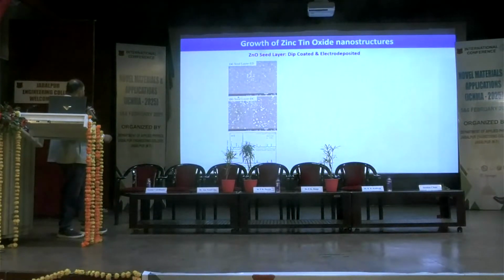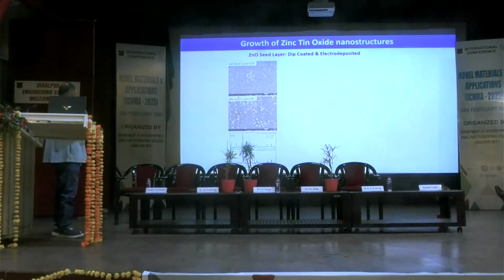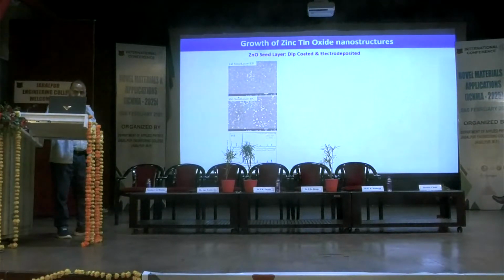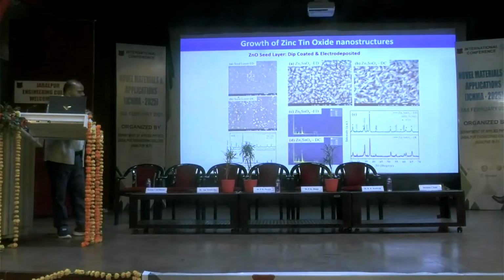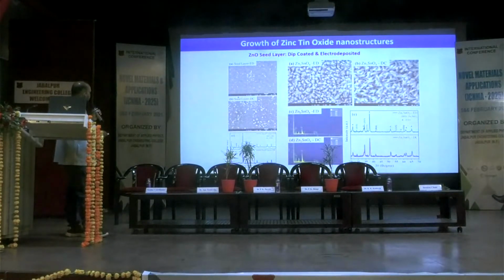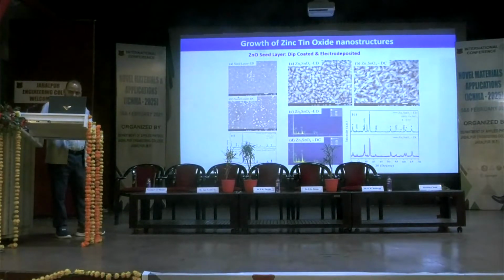So here you can see how the seed looks. Seed layer direct electrodeposition is more uniform and dense as compared to the dip coated. And this is the structure. If you look, they do not look very different, but they have differences. The electrodeposited one had a different structure, very tiny at the bottom, while the top surface looks slightly circular, thicker at the bottom and not so much at the top. Structurally it is almost the same, not very different in those seed layers.